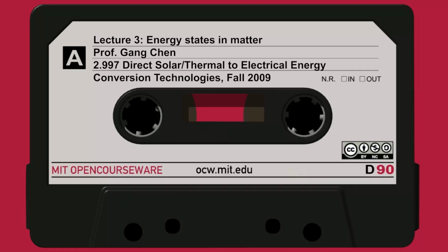And on the other hand, if I put boron into silicon, the outer shell has 3, right? So the boron energy level is somewhere here, close to the bottom of this band here. This is the valence band, this is the conduction band. So the energy level is here.